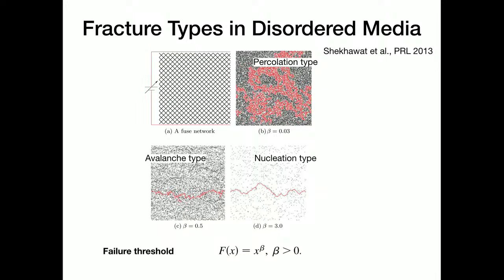So there's a lot of damage activity prior to final failure, and it is a very diffused form of crack path. The other extreme is when you have low disorder, that's high beta, when you have minimal activity in terms of damage prior to final failure, and you have a very well-defined crack surface spanning the width. This is the nucleation type fracture, where you have few nucleating events, and then there is growth of that, and you do not have independent nucleating events that grow independently until a significant amount of deformation, here increase in the voltage. And in between is the avalanche type, which is in intermediate disorder.